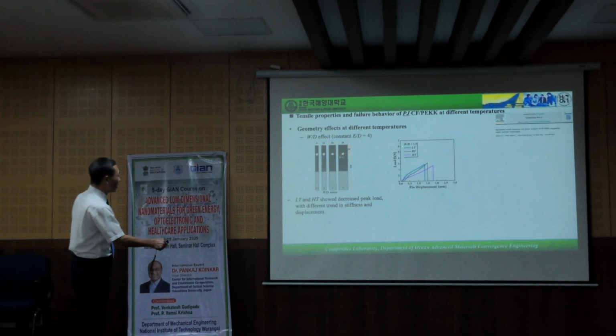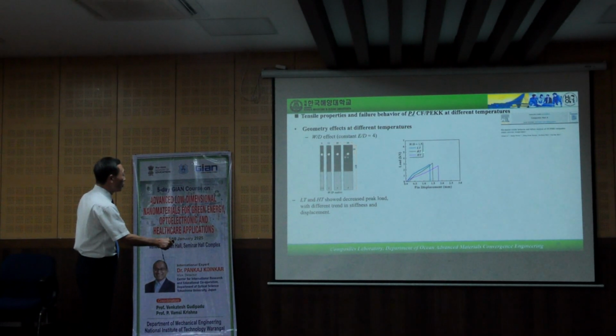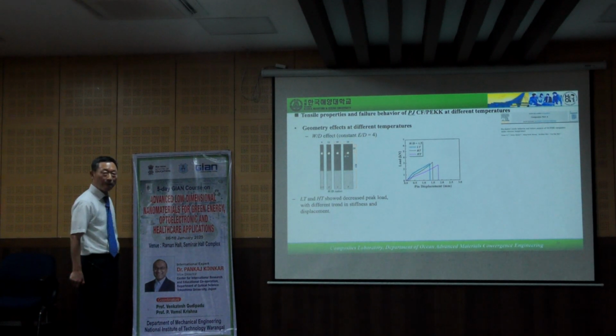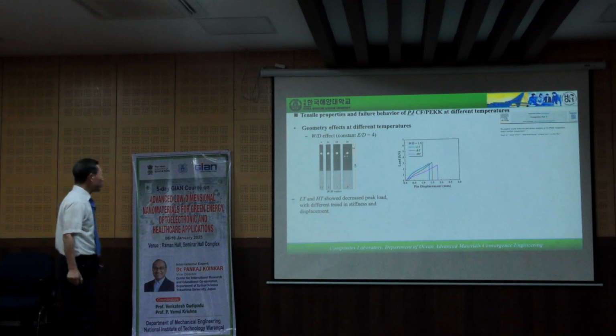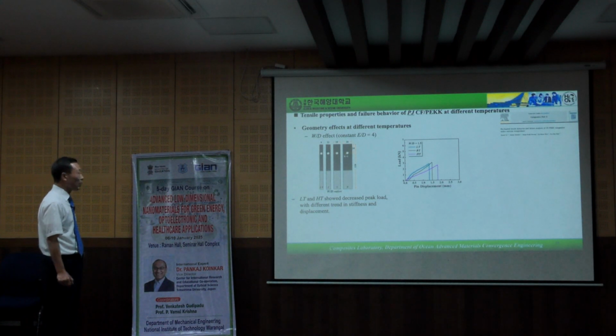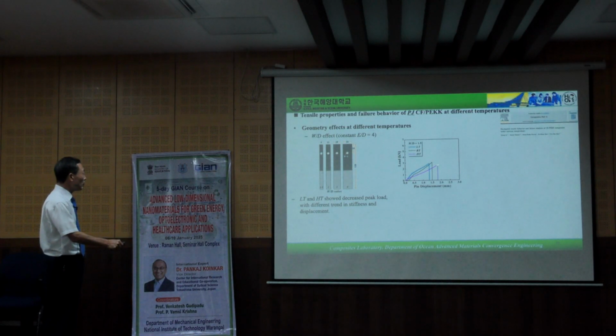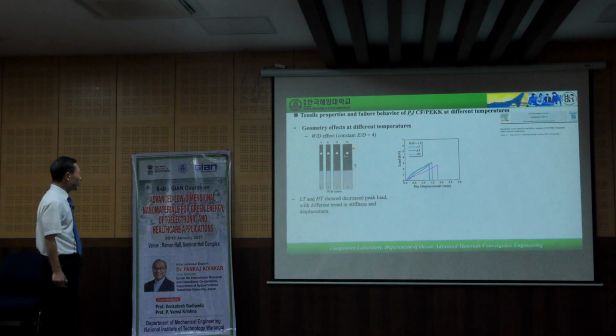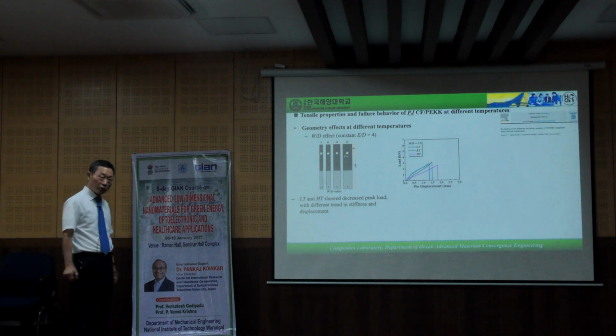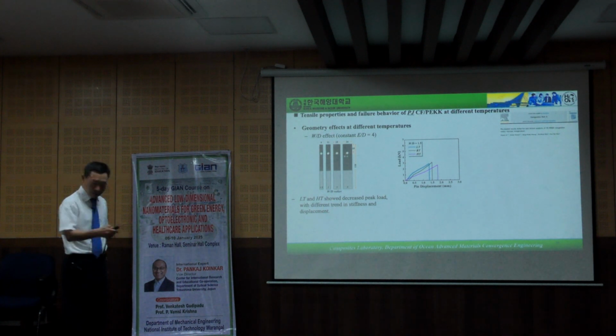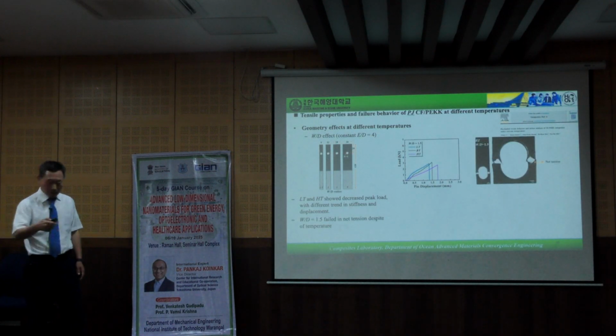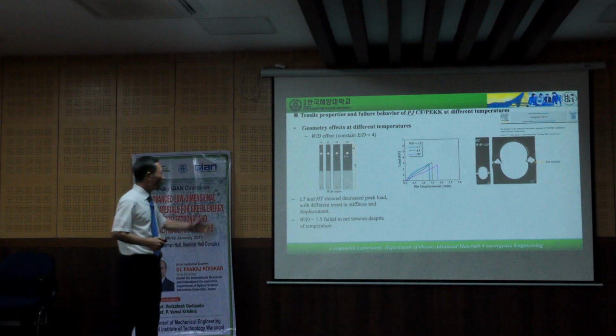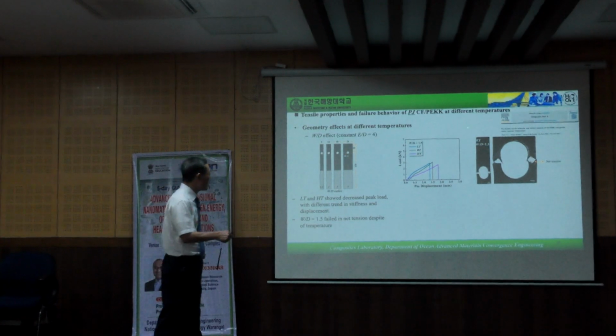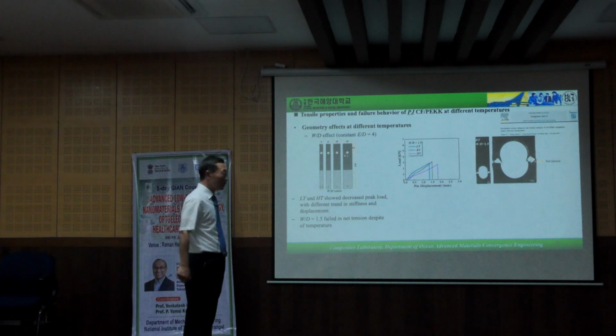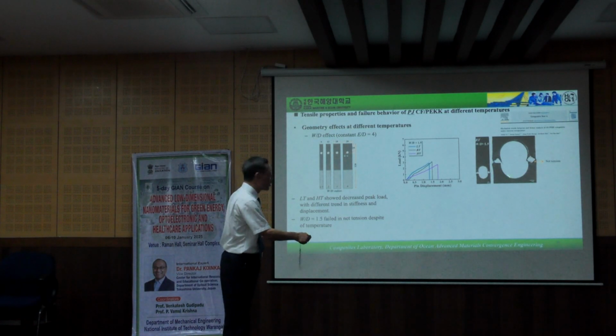In case of W/D equal 1.5, low temperature, room temperature, high temperature. Low temperature and high temperature showed decreased peak load with different trend in stiffness and displacement, right? Just look at the fracture behavior. In case of 1.5, net tension failure occurred totally.